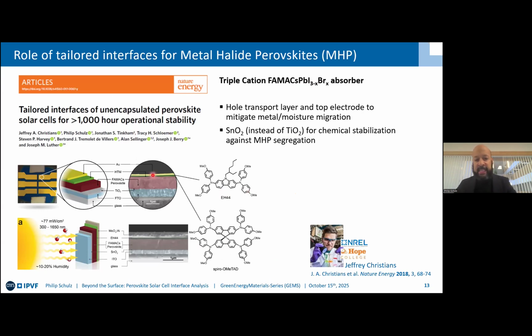by exchanging the interfaces. Here in that case, we started off with this triple cation mixed halide perovskite, spiro-MeOTAD as a hole transport layer and gold electrode. When you change the top, so you get away from the spiro to EH44, which is this molecule depicted here, and then also molybdenum oxide aluminum layer that mitigates metal and moisture migration into the perovskite. You enhance already an initial drop in power conversion efficiency over the first couple of minutes and hours, and then this was really key to it, substitute the bottom titanium oxide layer by tin oxide, you get to chemical stabilization against metal halide perovskite segregation.